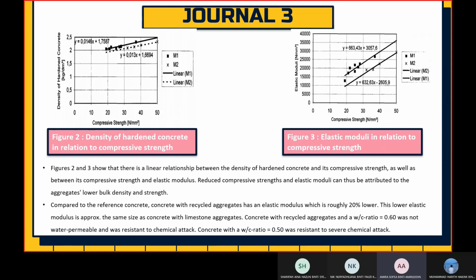Figure 2 and Figure 3 show that there is a linear relationship between the density of hardened concrete and its compressive strength, as well as between its compressive strength and elastic modulus. Reduced compressive strength and elastic modulus can thus be attributed to the aggregate's lower bulk density and strength. Compared to the reference concrete, concrete with recycled aggregates has an elastic modulus which is roughly 20% lower. This lower elastic modulus is approximately the same size as concrete with limestone aggregates.